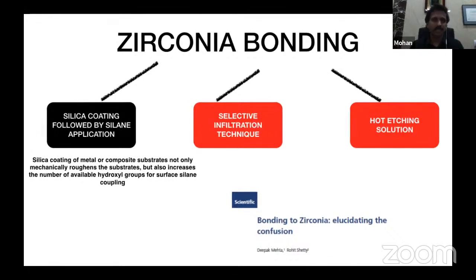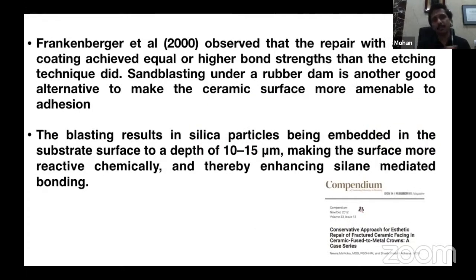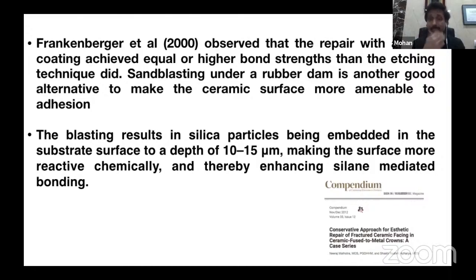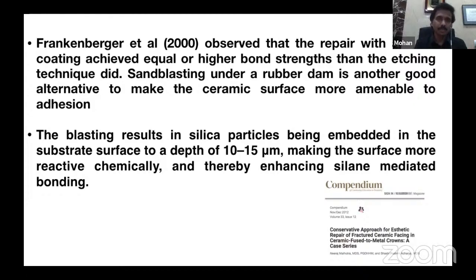So I'm not going to discuss more on that, but silica coating, what they have told is that it's like air blasting, right? You apply silica, that would definitely improve. That's what Frankenberger et al. told, that when sandblasted, of course with the rubber dam, the silica obviously penetrates into the zirconia porosities, and that forms a good base for the adhesive or the coupling agent to stick on. So that is why, with a zirconia fracture, generally people will not want to do a mini repair. What they'll do is apply the silica, make sure that the substrate becomes better, and then proceed further with the repair of the zirconia. So please, when it comes to zirconia, let the red bell ring to you: am I going to repair this seriously?